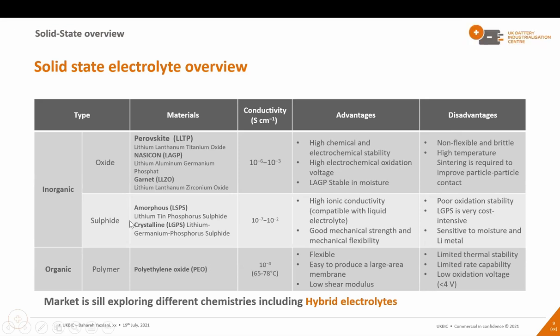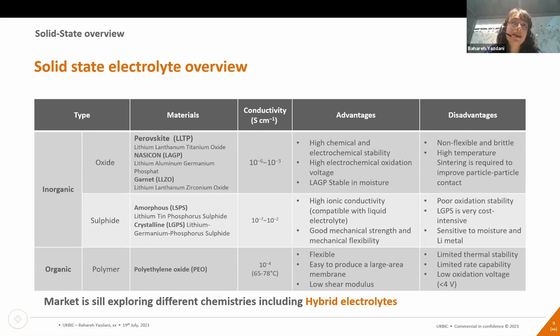However, some of the sulfides, including LGPS, have a very high ionic conductivity, even at some points comparable with liquid electrolyte, which is very good because we don't have to compromise on the conductivity. And they also have very good mechanical flexibility, which is very beneficial for reducing the manufacturing cost. However, they are very sensitive to moisture, and then they will generate dangerous H2S gas, and also some of them are not completely compatible with lithium metal, which is appealing for solid state, and they need some interlayer engineering to be compatible.